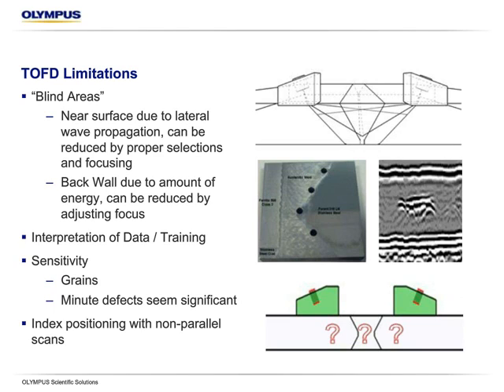Some of the limitations. So the blind areas we talked about earlier, we call them blind. A lot of people call them dead zones. I don't like to use this term. At the top, there will always be what could be called a dead zone. So there's a small area, typically a couple of millimeters depending on your setup and some other factors, but this is because it's not really a surface wave, so that wave needs a little bit of material to travel in. There will always be a small zone that we're not actually covering with a single TOFD pair.